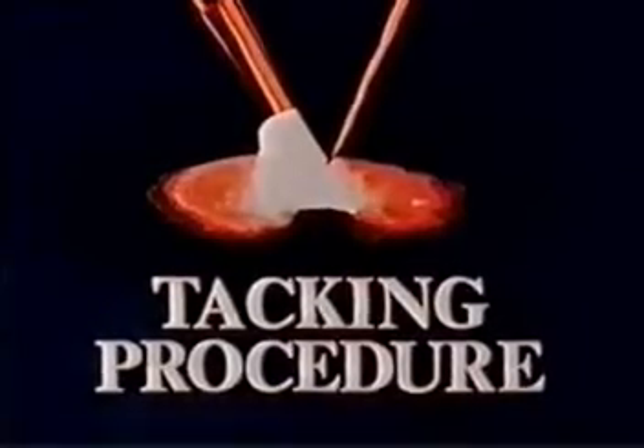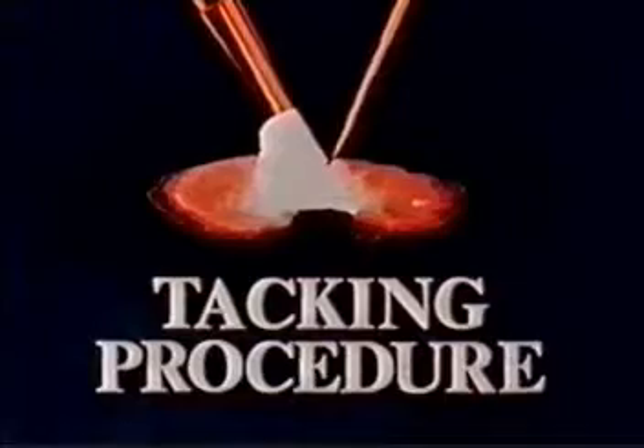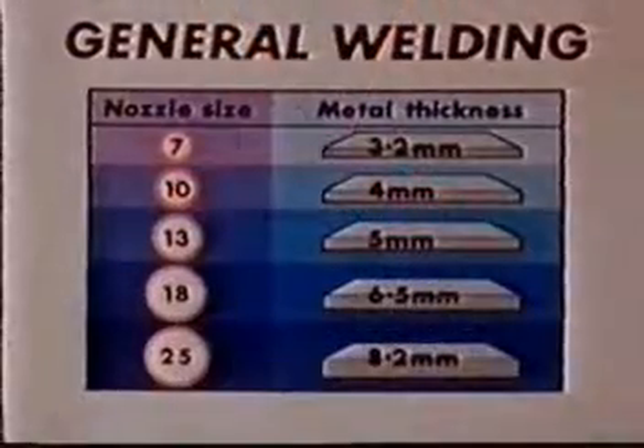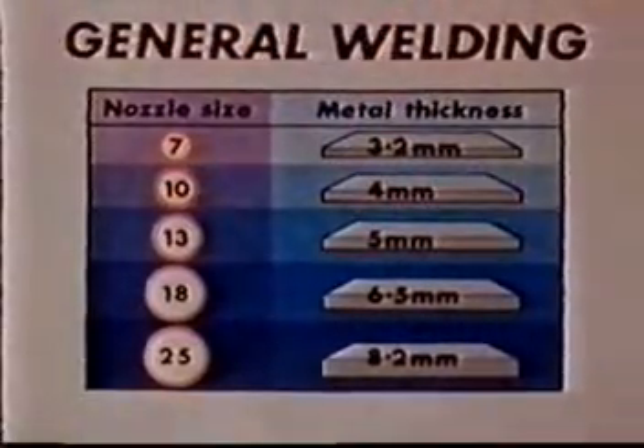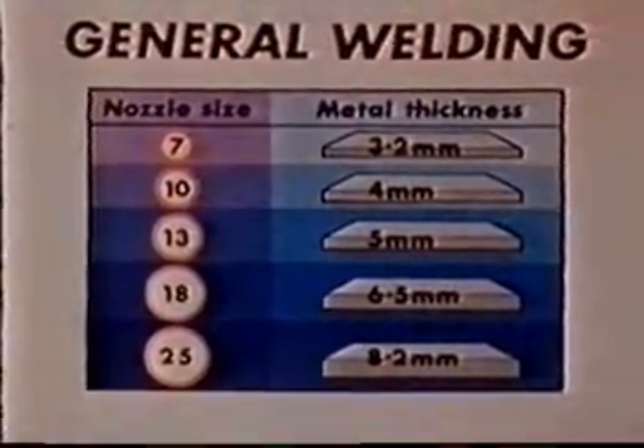To ensure maximum control of the molten pool, it's important to choose the correct nozzle in relation to the metal thickness to be welded. Tacks must be fused to the full depth and shaped on each side, making pickup or restarting easier. Notice how the square edge is in effect being beveled to the full thickness of the metal.